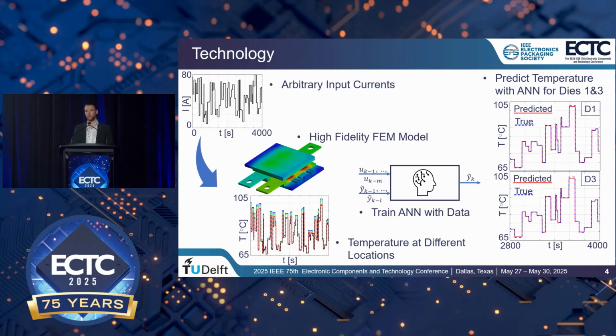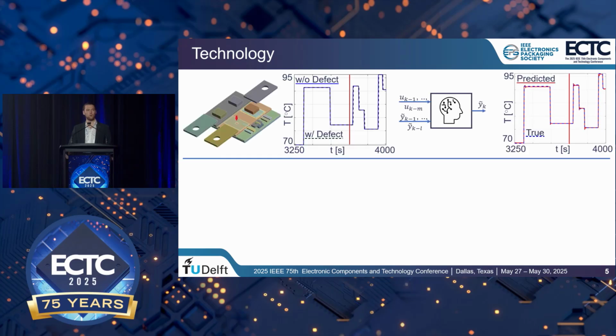Now, let's go to the second scenario. We made it a bit more realistic. We added a little defect in the sinter layer of the die attach. This defect is about 2.5% of the total sinter area. We simulate it again, and we see a slight shift in the FEM model output. The red line is where the defect becomes apparent. But we don't see a change in steady state temperature.